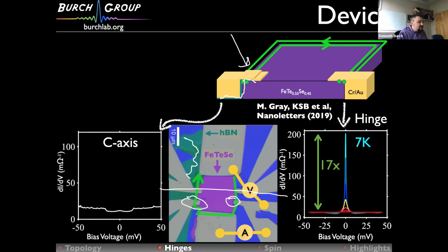Now to compare that, our C-axis contact, which by the way had basically the same normal state resistance as the contact that touches the hinge. So there's no reason to think that it's just a crappier contact or anything like that. Now I've zoomed in by a factor of 2 for the dI/dV versus voltage, and we see a little feature. If I zoom in by a factor of 10, we see what looks like a zero bias peak, but it's misleading. It's just that the temperature is too high.